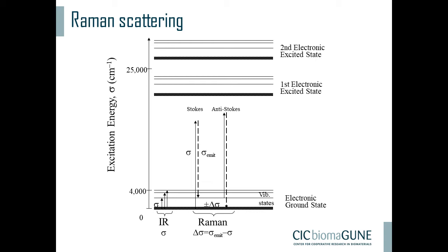However, it was discovered in the 1970s that if you're looking at molecules that are in contact with, in that case, roughened metallic electrodes, nowadays we would say nanostructured metallic systems, then you can obtain the same spectra, but amplified by many orders of magnitude. And the reason behind that is, as I already mentioned earlier, you are creating a very high electric field, which will affect the polarizability of the molecules if they are close enough to the surface. And then the probability of the Raman scattering transition will be enhanced a lot.